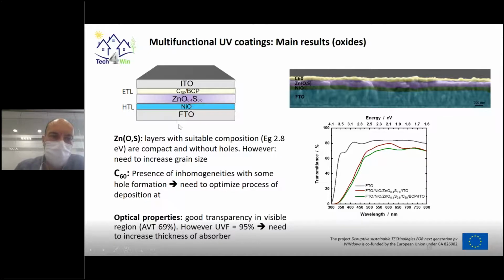This is integrated in a device that has been synthesized on FTO substrate, combining a nickel oxide hole transport layer and a compound electron transport layer combining a C60 and a BCP layer. Here in the right-hand side, you can see an SEM cross-section of the device structure, where we have colored the different layers for easy identification. What is very interesting in the oxosulfide layer is that we can achieve really very compact and continuous layers without the presence of holes.